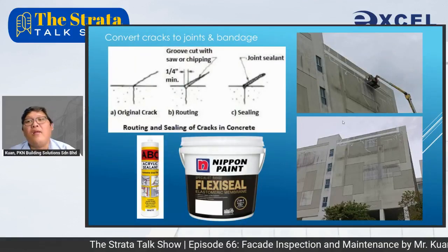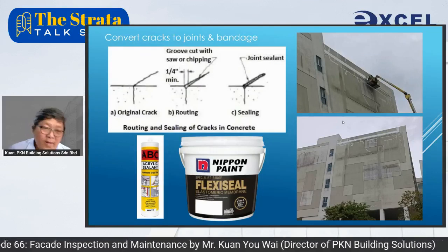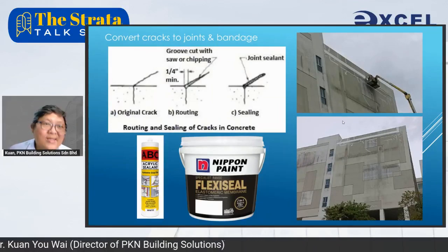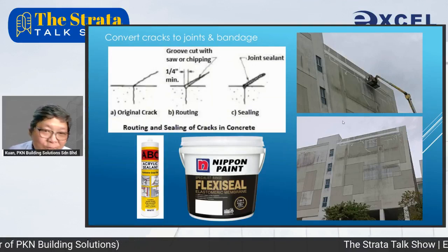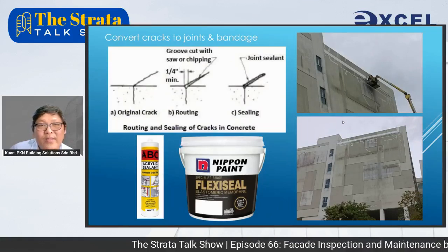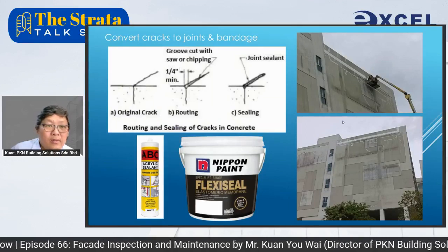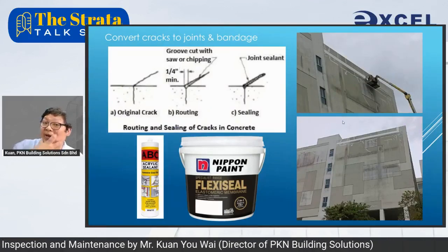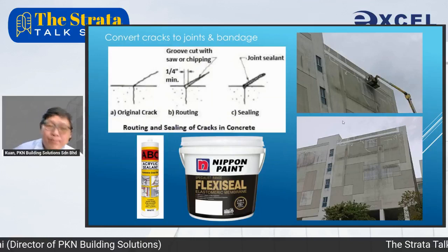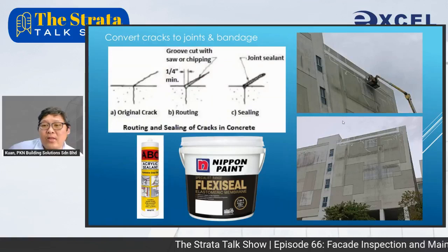And of course, when it comes to repair of cracks, bear in mind it is often too expensive to know if this is a natural shrinkage crack or a heat-induced crack. So my principle is, in the event that we need to repair a crack, please use elastic material like acrylic paintable sealant. Do the diamond cutting, routing, and then seal it with acrylic paintable sealant. Prime it with elastomeric primer before you do the finishing coat.